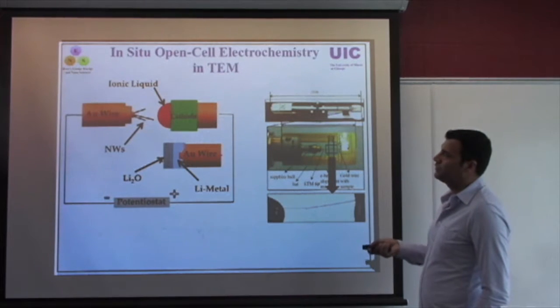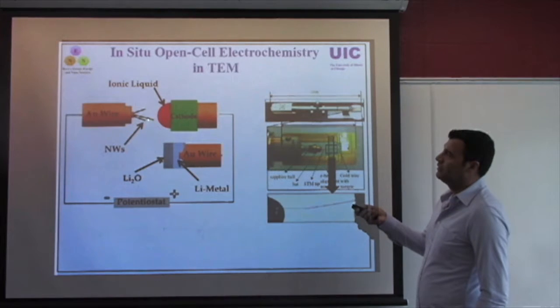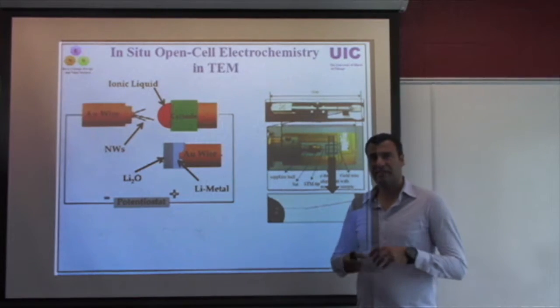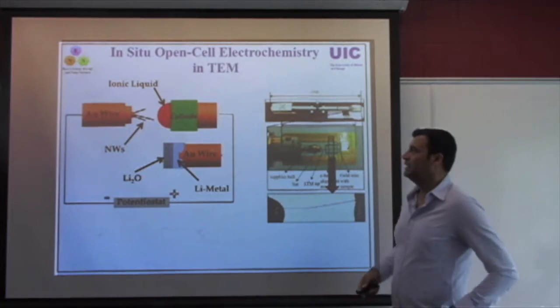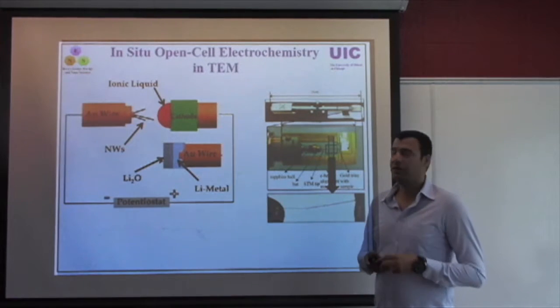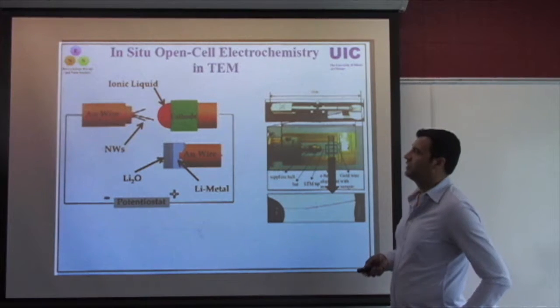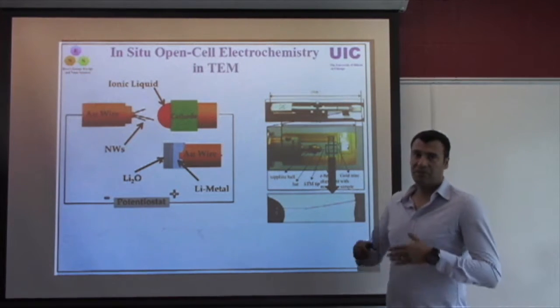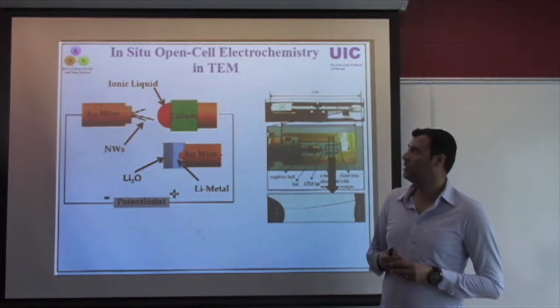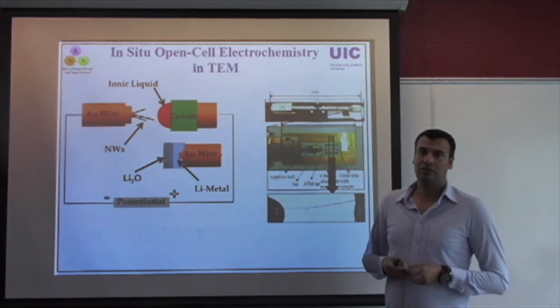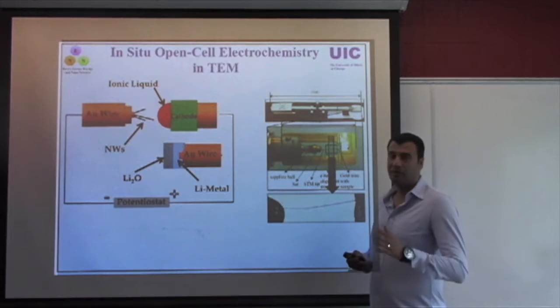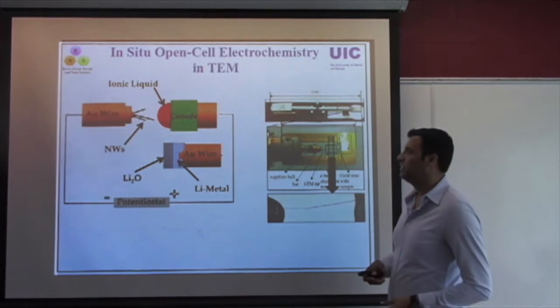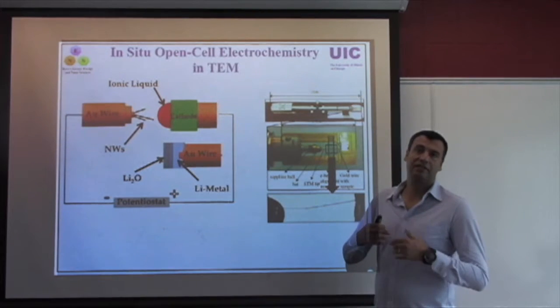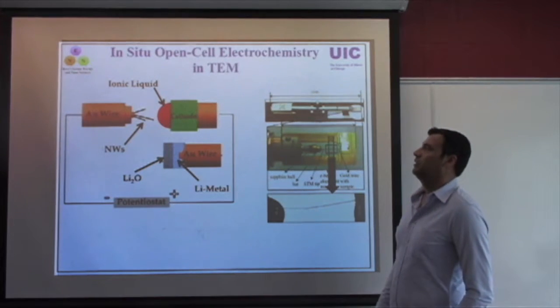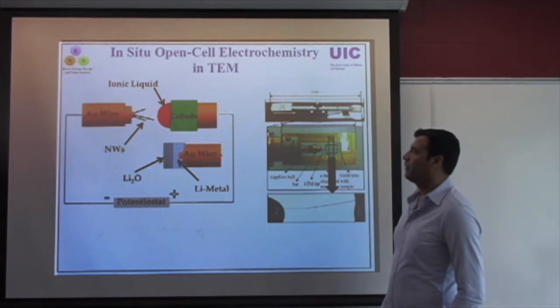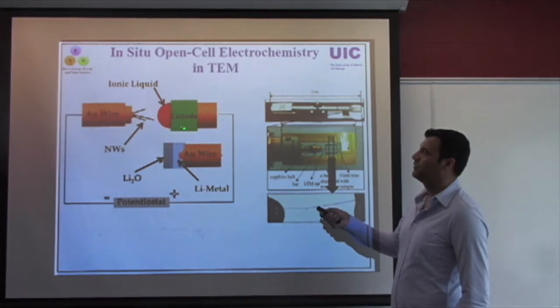So in order to study the electrochemical reactions at nanometer and sub-nanometer, the best system to use, at least in my opinion, is the open cell configuration. In this system, because we don't have any sealing membranes, then we can gain resolutions that are far better, could be even 100 times better than systems that are using silicon nitride or any other sort of liquid electrolytes to observe the reactions.